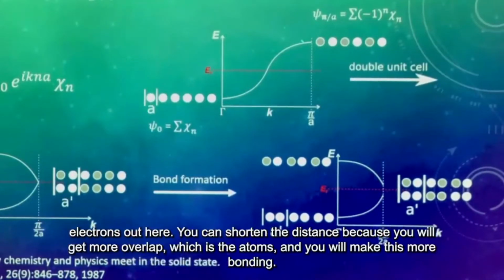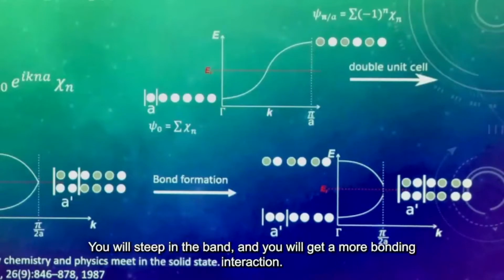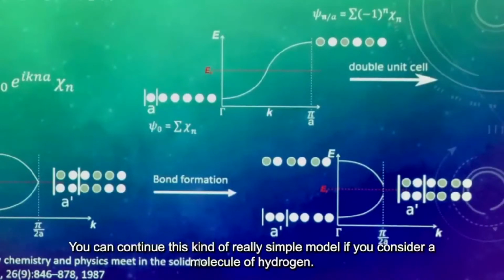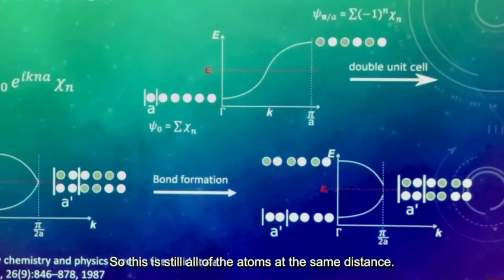The other thing that you know is that this is an anti-bonding part of a band. So if you start taking electrons out here, you will shorten the distance, because you will get more overlap between the atoms, and you will make this more bonding, you will steepen the band, and you will get a more bonding interaction. You can continue this kind of really simple model if you consider a molecule of hydrogen.